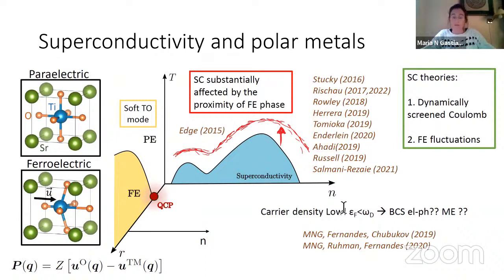This is a challenging regime, because if you want to couple to modes that are at much higher energies, you have to be a little bit careful with the formalism that you apply. So what I'm going to do today instead is couple these electrons, which have very low Fermi energies, with a mode that is very soft. And the fact that it's very, very soft puts it in a regime where, if my mode is about 1 meV, even if I have a Fermi energy of 10 meV, it's still in the conventional adiabatic regime. And then in principle, all these BCS, Migdal-Eliashberg tools are okay to be used. So this is something that I wanted to point out. This is one of the big challenges, and I'll say a little bit more about that at the end of the talk.